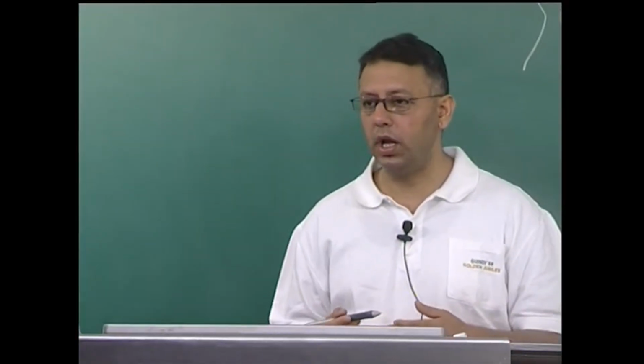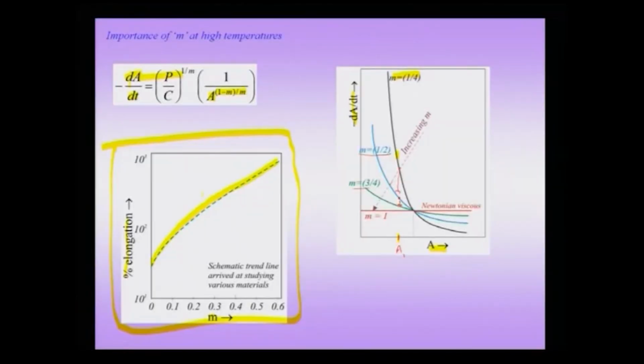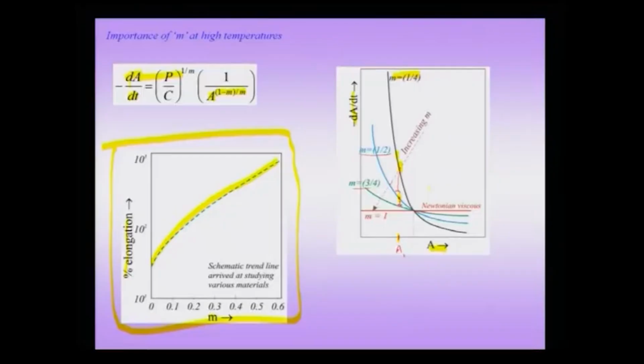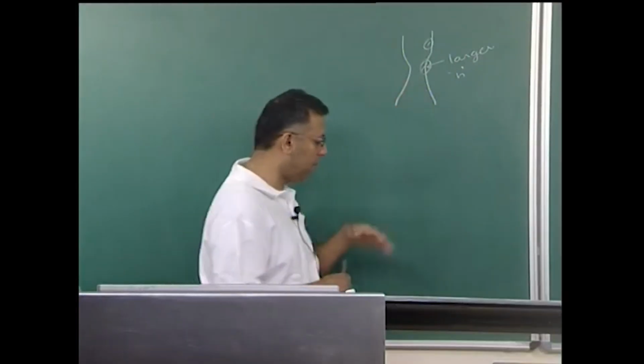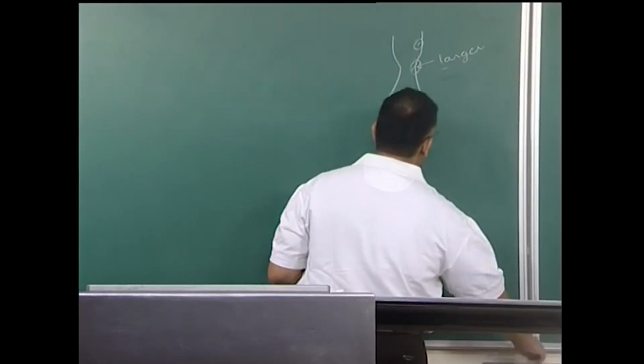If I look at reduction in cross sectional area per unit time, I would have a curve for each one of the materials I am studying, and for a given cross sectional area, the reduction would be more for a material with low m as compared to a material with high m. Therefore, the higher the m, the smaller would be the reduction in cross sectional area with time. This also can be understood by plotting experimental results for various materials, and you see that with increasing m there is an enhanced ductility, and the explanation is very similar to what I told you for n.